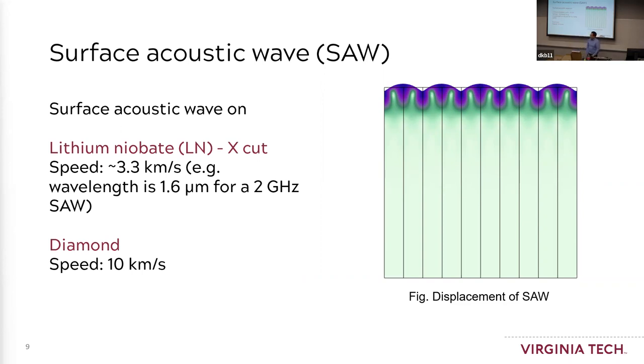These numbers are so important because at this point, 1.6 micron is relatively easy, or at least feasible, for nanofabrication technologies at this scale. And 2 gigahertz is just a typical number for microwave signals. For people who want to go to higher frequency, another platform we explored is using diamond. It is a very hard material with very high Young's modulus, so you can push the speed to 10 kilometers per second, and for sure you can also push the frequency of the acoustic wave devices.